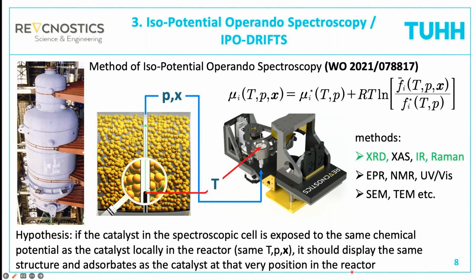And when we do it like this, we can address these three challenges that I showed on the slide before. We can study a catalyst inside any arbitrary reactor. We can use a spectroscopic cell that is perfectly designed for the spectroscopic method, and we automatically measure those conditions which are interesting for the reactor, because we take the conditions directly from the reactor. So this is a quite useful approach, and it is not restricted to IR spectroscopy.